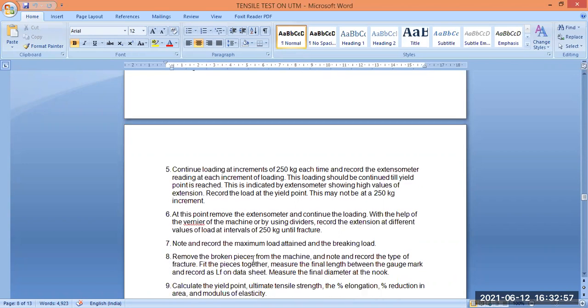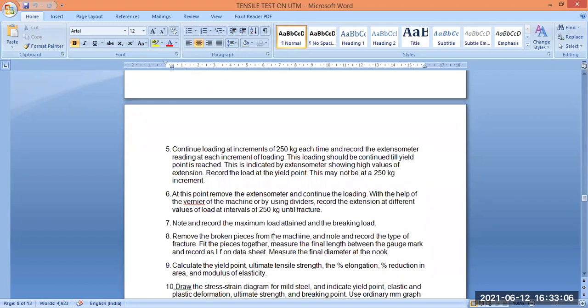At this point, remove the extensometer and next record the maximum load attained at the breaking point. Remove the broken parts from the machine and note and record the type of fracture. Fit the pieces together, measure the final length between the gauge marks and record it as LF on the data sheet. Measure the final diameter of the neck by means of the micrometer.